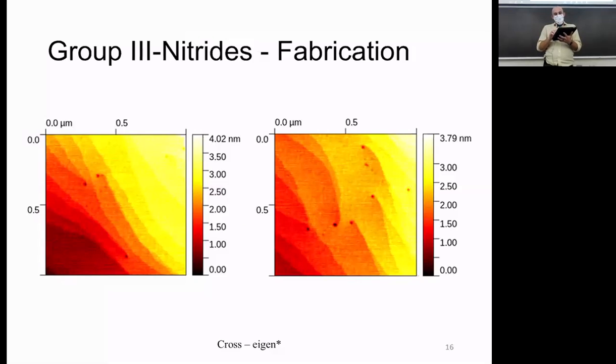There's also some pretty cool things right here. If you look on this picture, there are these holes right here. And those holes are called pinholes. And around them, you can actually see a screw dislocation. So what that is, is a layer of crystal that spirals down. Instead of being 2 separate layers, it makes its own second layer. It's not what we want to see, but it is something cool to look at.